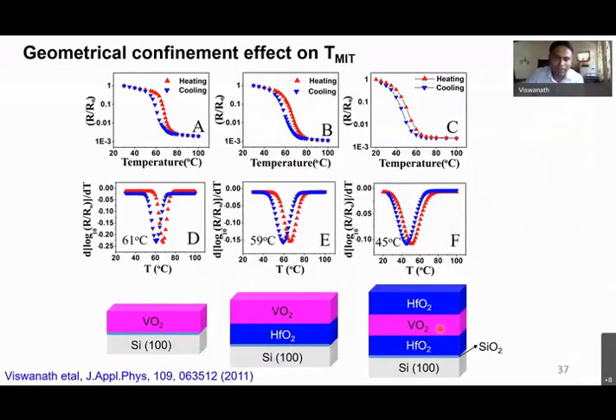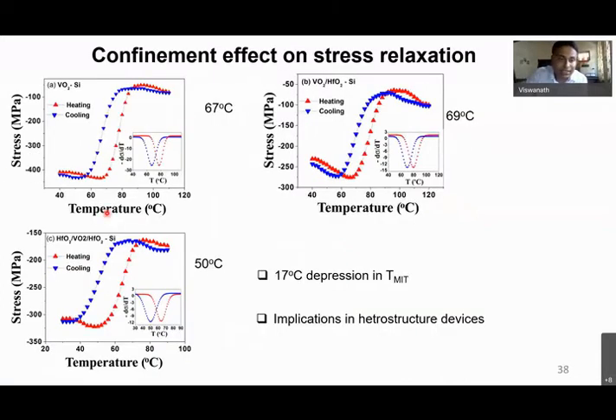So I'll give you 2 examples. VO2, we can deposit as a thin film on silicon. You can also make VO2 sandwiched between 2 hafnium oxide layers. Because of the confined sandwich structure, there is a possibility of compressive stress acting on it. We have measured both resistance as well as stress. We found the transition temperature is going from 61 degrees Celsius to 45 degrees Celsius. That is again a transport measurement.